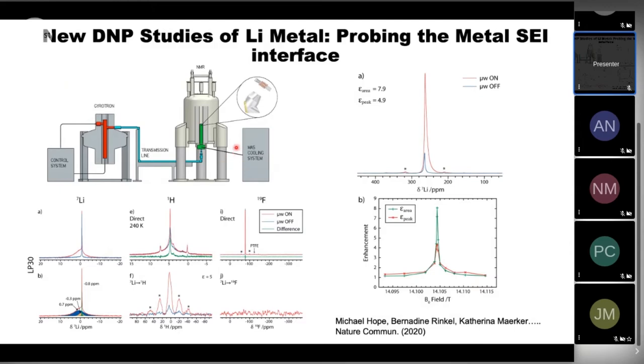And here we're going back to very early DNP experiments that were originally invented for lithium metal, using the unpaired electrons in lithium metal to polarize the lithium nuclei. And so this is an example now of lithium metal with and without the microwaves. The microwaves are used to excite the electrons, and in blue is without microwaves, and in red is with microwaves. And so we can see basically the lithium metal signal as was done by Charlie Slichter and others more